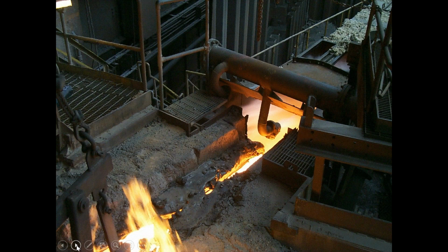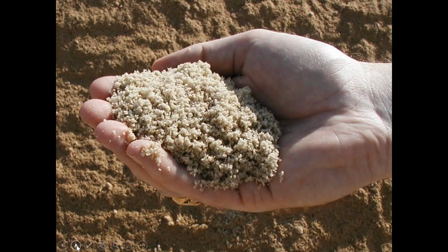And this is the journey of turning slag into cement. What you see here is the granulator. The purpose of the granulator is to impinge high amounts of water to turn it into what you're seeing in that gentleman's hand. If you look closely, you can see little whiskers. And in fact, it is between 90 and 93% glass. That's the purpose of taking that material from its molten stage and turning it into the raw material for slag cement. So in the past, we used to talk about granules. This is granules, and slag cement was referred to as ground granulated blast furnace slag.